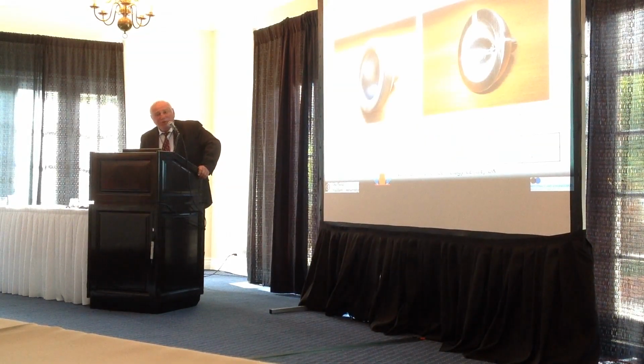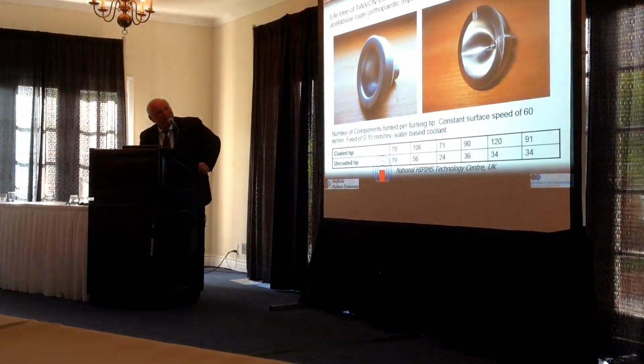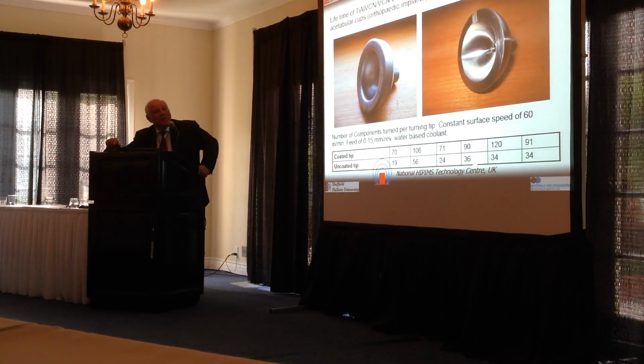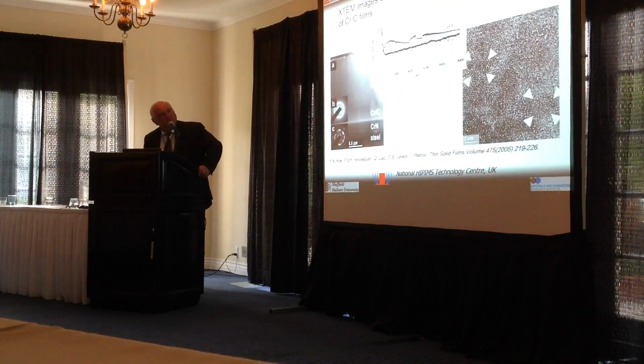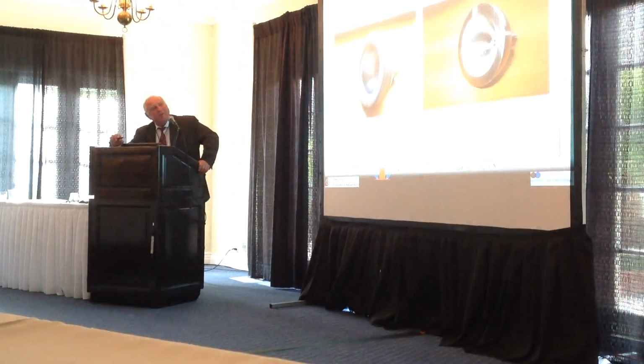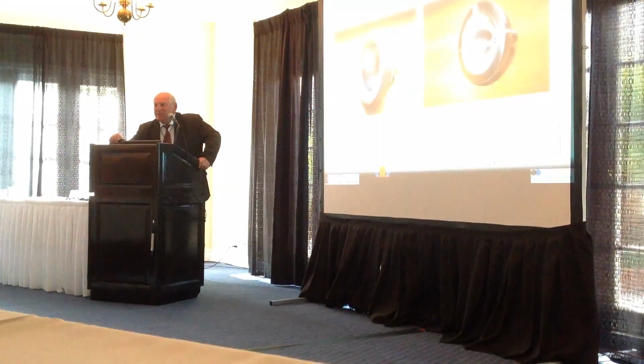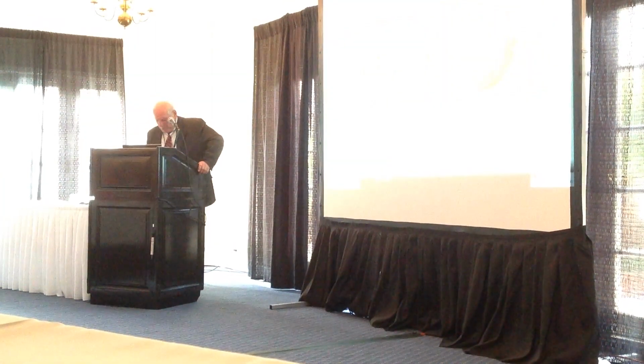But we were also very good in machining titanium alloys. And this is a case where we show that we can improve the lifetime of our tool by almost a factor of 3, by machining 3 times more components for medical implants. So we cannot explain these results by saying, okay, our coating is inert. Because if it is inert to aluminum, it definitely reacts with titanium. This coating has a different wear mechanism.